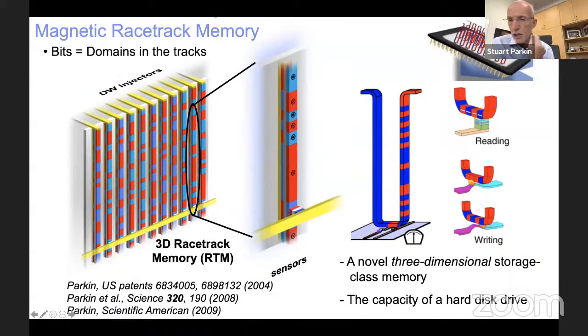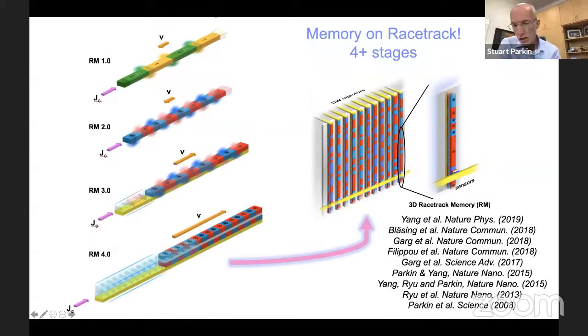The concept was that if you pass current through this homogeneous magnetic wire, you can move all of the walls between the red and blue regions in the same direction synchronously. And in so doing, you can put, let's say, 100 or 200 bits of information in a single nanowire and increase the performance or the storage capacity by 100 times compared to any conventional memory technology. What's exciting is that when I first proposed it, this basic concept of manipulating domain walls with current wasn't demonstrated. And we did that within a few years. It took quite a few years. So I want to briefly discuss the evolution of racetrack memory, from a concept to an actual device over the last decade. I'm not going to do that in too much detail because it would take too long.